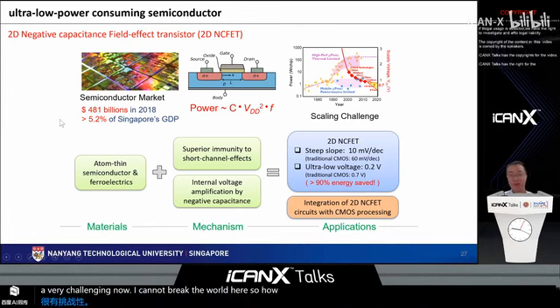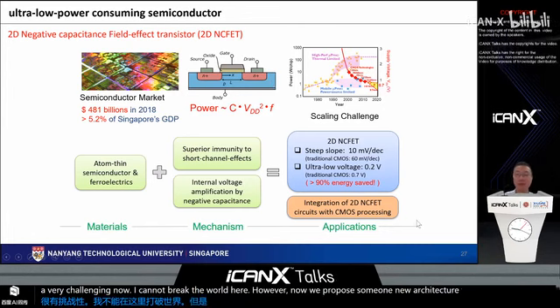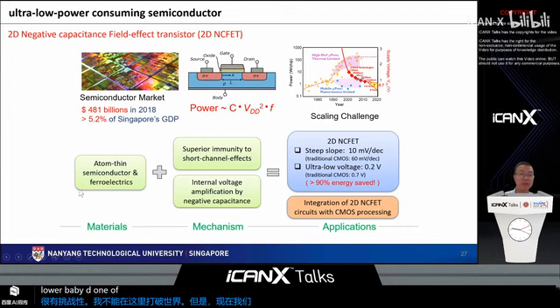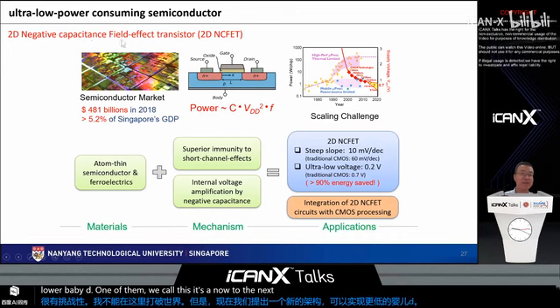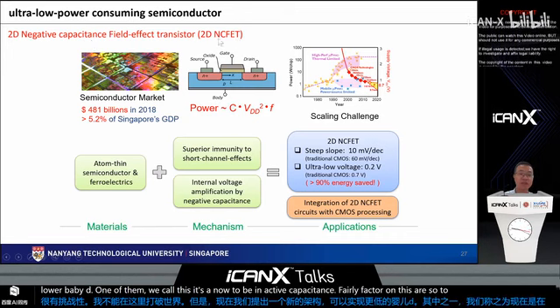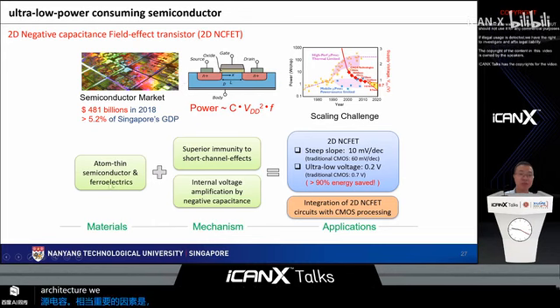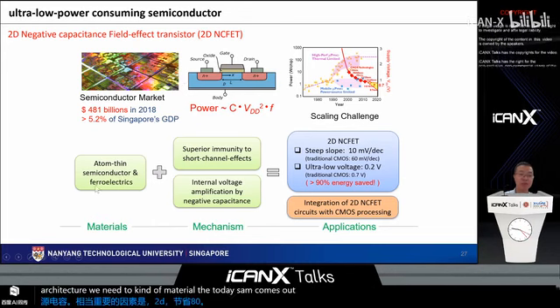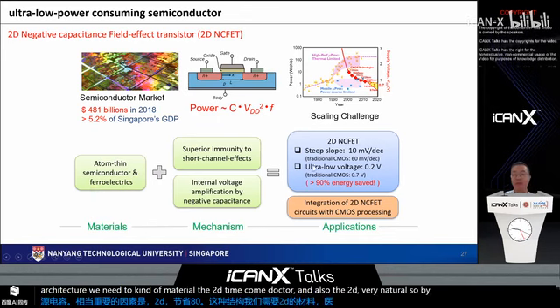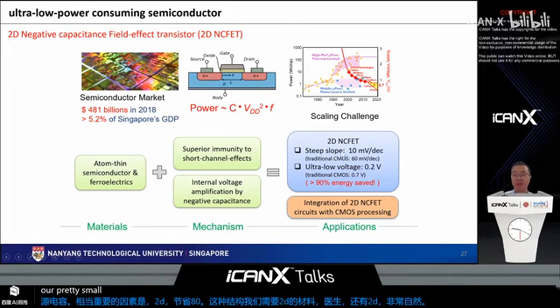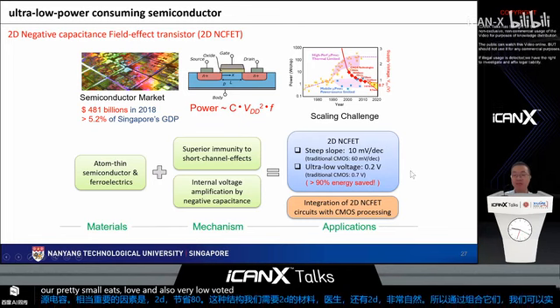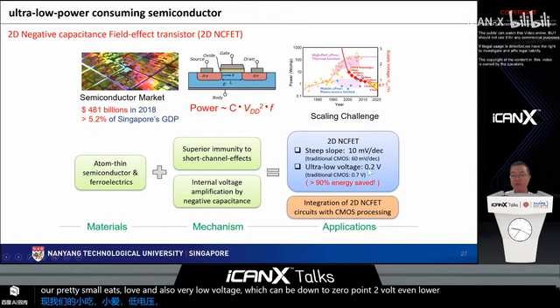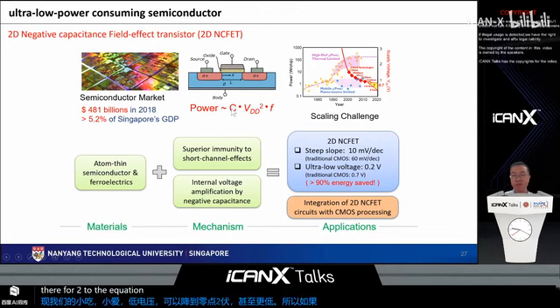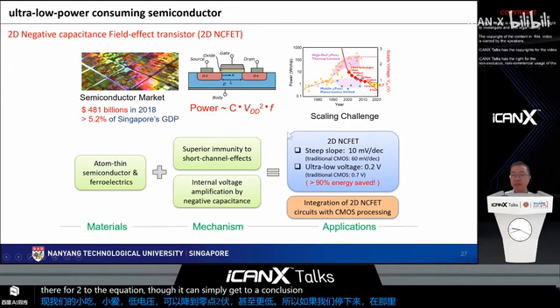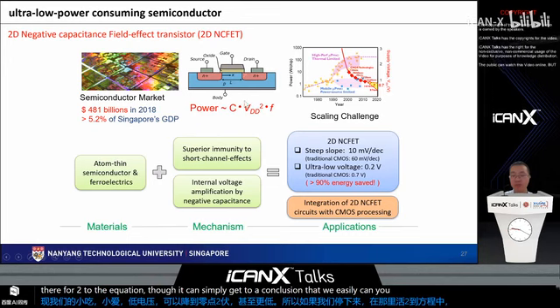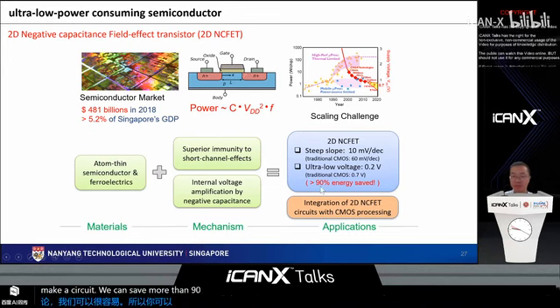However, now we propose some new architecture that may realize even lower VDD. One of them, we call the 2D negative capacitance field effect transistor, 2D NCFET. For this architecture, we need two kinds of material, the 2D semiconductor and also the 2D ferroelectrics. By combining them, we can realize a pretty steep slope and also very low voltage, which can be down to 0.2 volt, even lower. So if we substitute this value, 0.2, into the equation, we can simply conclude that if we can use the 2D NCFET to make a circuit, we can save more than 90% of the energy.